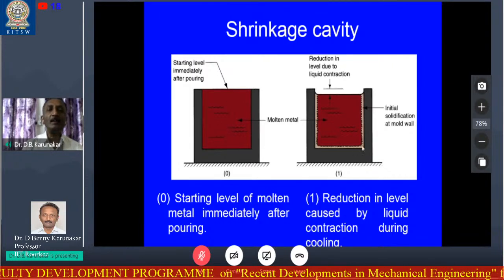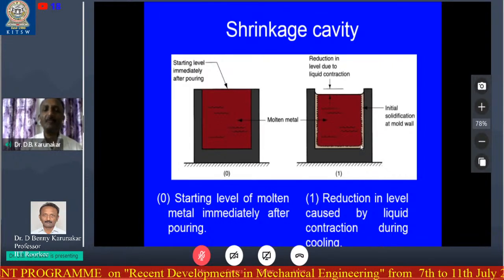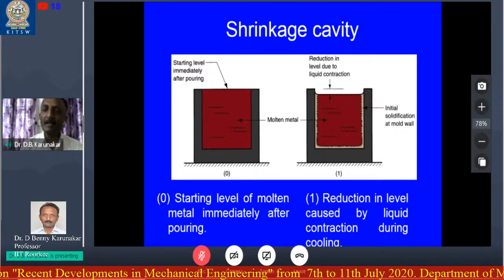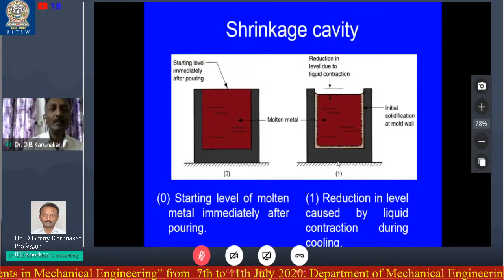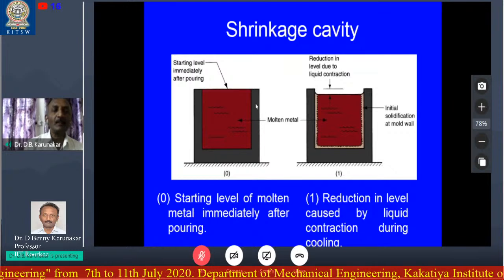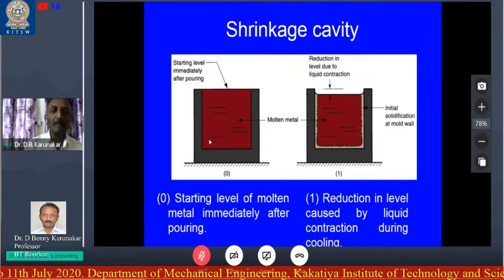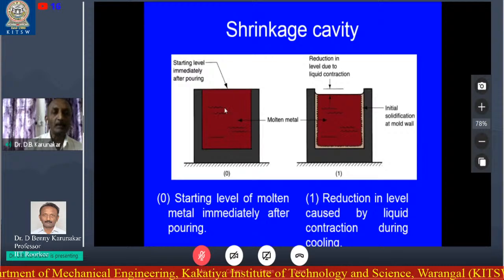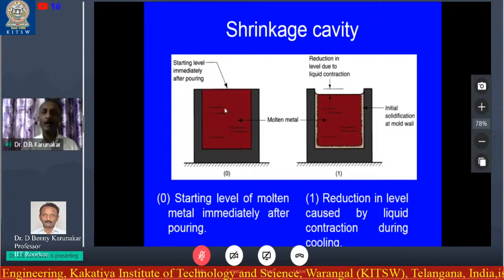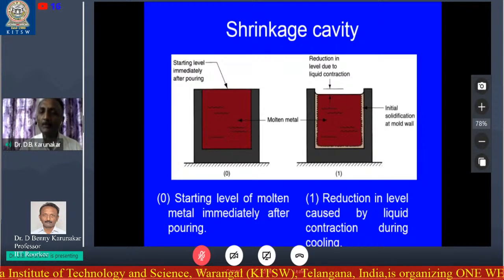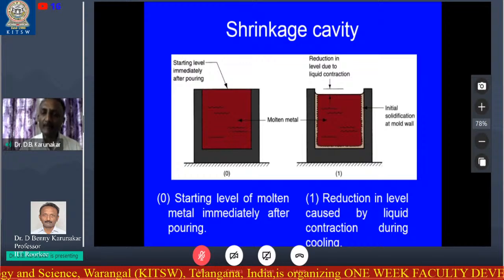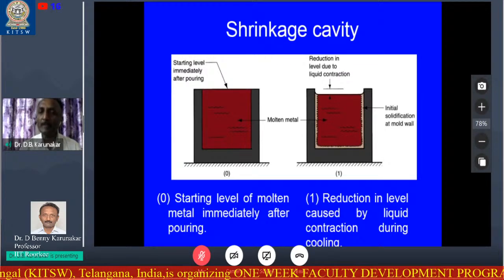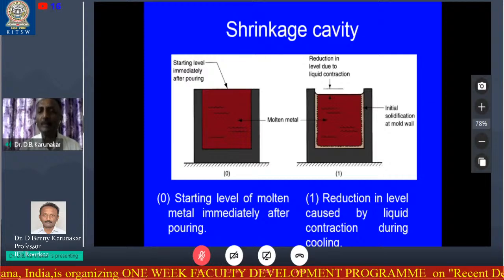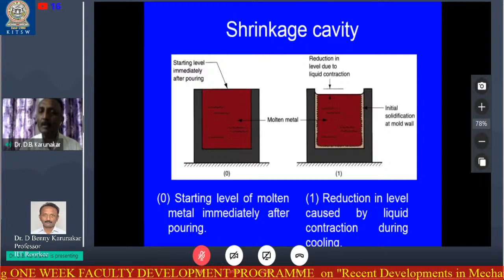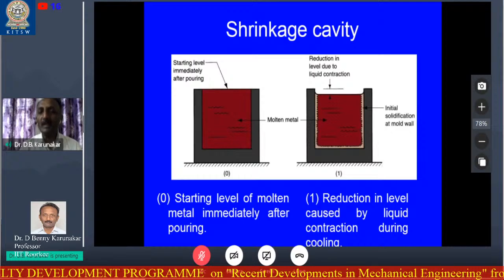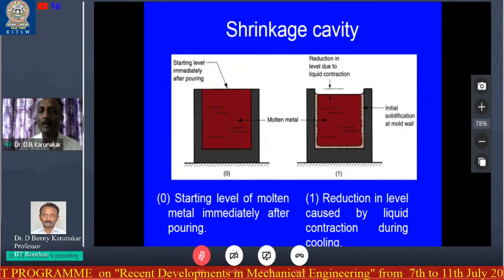Now you can see here there are 3 types of shrinkages for any metal. One is the liquid metal shrinkage. See, in a vessel or in a container, we have poured the molten metal. Initially, it is like this. Now we have seen there are always 2 temperatures for any cast metal. One is the melting temperature. The other one is the pouring temperature. Pouring temperature is always higher than the melting temperature, maybe higher by at least 100 degrees centigrade above the melting temperature.